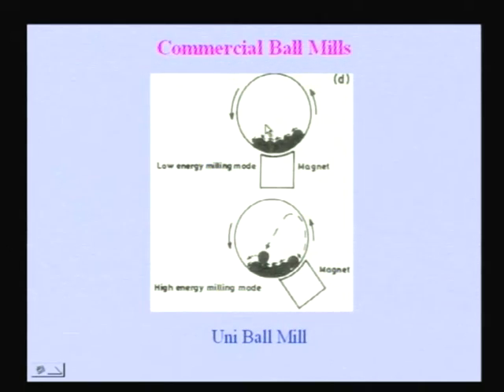So, now depending on where you place the magnet and start rotating the bowl or the container, the balls are taken to a higher position depending on the position of the magnet. If the magnet is exactly at the bottom, then definitely balls will not go very high, because the magnet is attracting these balls, and these balls are basically steel balls. So, steel balls are attracted by the magnet. So, the balls will not go to a very high position here, and so basically they will keep on moving there itself. So, there is not much impact, but only some shearing process will take place.